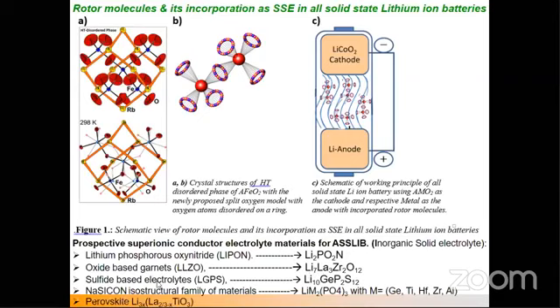So for example, take the sulfide-based electrolytes. You have PS4 tetrahedra in Li10GeP2S12, which shows a conductivity of 10^-2 Siemens per centimeter. So they show very high conductivity. The mechanism is that the PS4 tetrahedra rotate the way I've shown in the previous slides, and the rotation of these PS4 tetrahedra at a particular triggering temperature boosts the conductivity of lithium manifold.